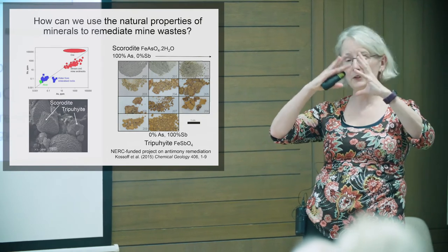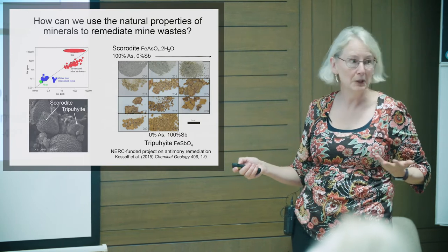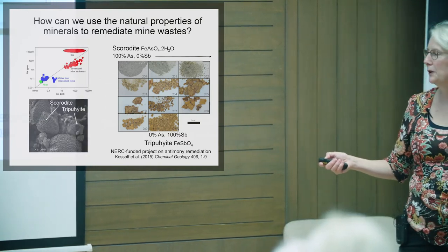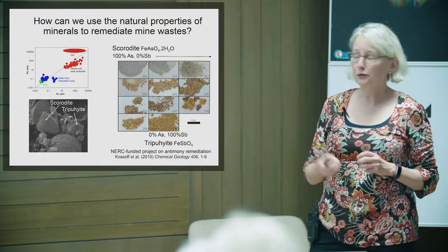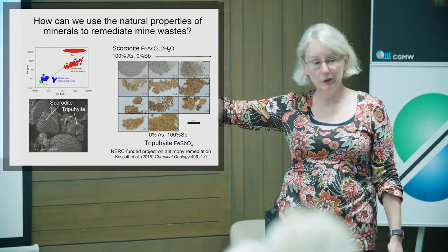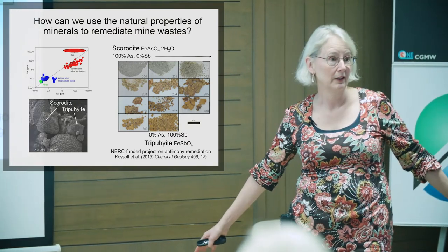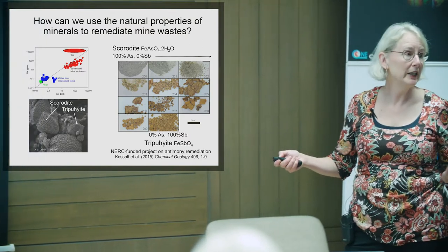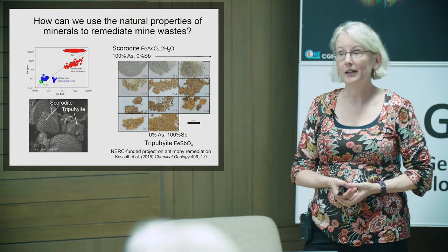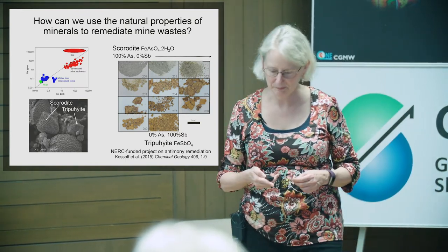You should have realized that, but it's too big. It's really big compared to the arsenic. What it did is it made its own mineral called tripuhyite, which is a great name, FeSbO4. But the great thing about tripuhyite is that it's really insoluble. David, the postdoc, tried to dissolve it in hydrofluoric acid, and it would not dissolve. So in the environment, tripuhyite might be a way to store antimony away and remediate antimony sites. So that's something we're hoping to pursue someday.